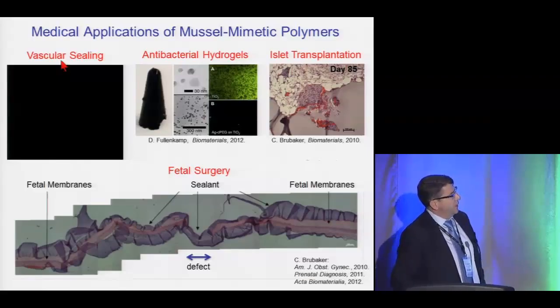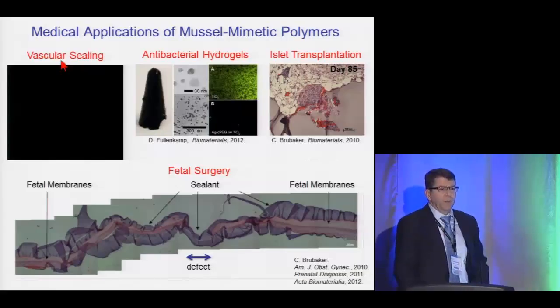So we've explored in a number of contexts the medical applications of these gels. I don't have time to show you a video of vascular sealing, but this is one of the earliest applications that we explored. Antibacterial hydrogels, actually, if you use as the oxidant to drive the oxidation of the catechol to the quinone, if you use silver ions, the silver gets reduced to form nanoparticles. Silver oxidizes the catechol. You get the cross-linking and adhesion. And embedded within the gel are silver nanoparticles, and these are very good for antibacterial properties.